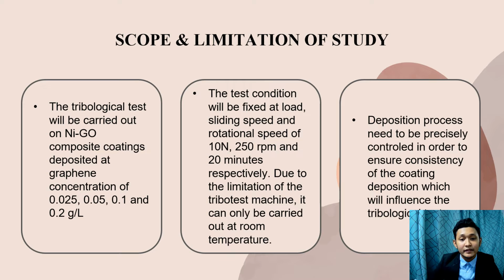Scope and limitation of study: the tribological test will be carried out on nickel graphene oxide composite coating deposited at graphene concentrations of 0.025, 0.05, 0.1, and 0.2. The test condition will be fixed at load, sliding speed, and duration of 10 Newton, 250 RPM, and 20 minutes respectively.